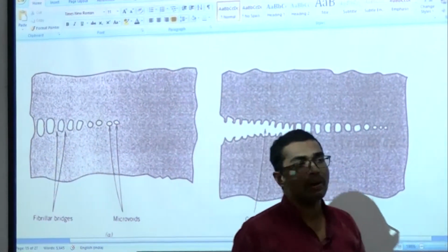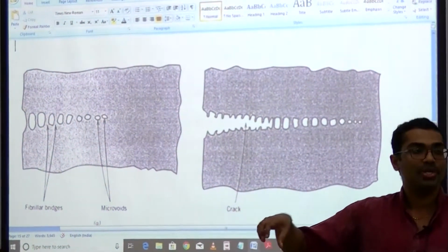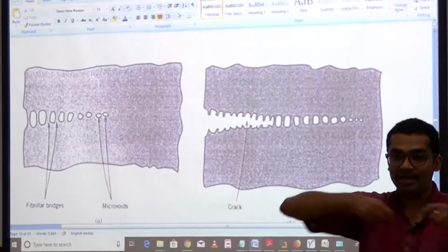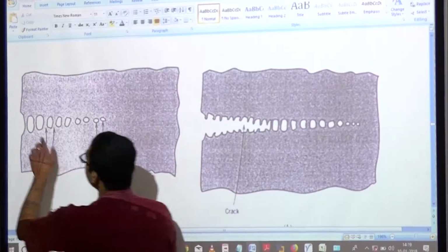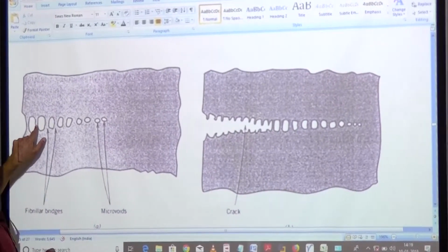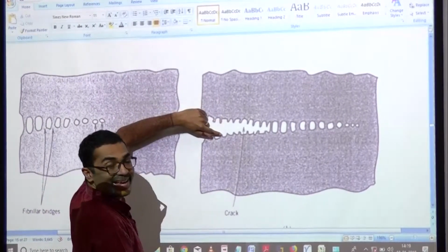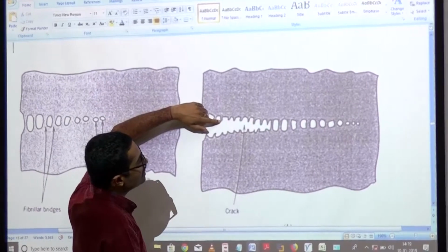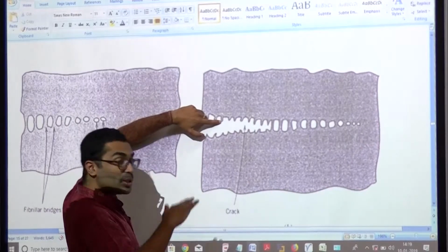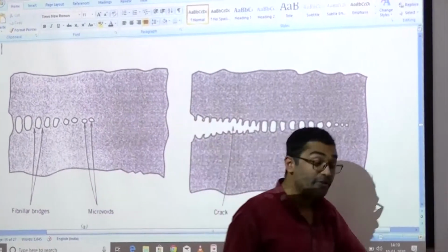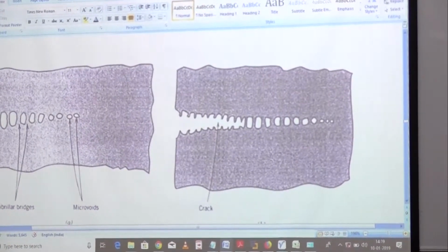And this is again perfectly analogous to what you would expect even in a metal, let us say very close to its melting point. You apply stress, and then you would have stress distributions that can result in micro voids and so on. And notice that this region is essentially where necking is happening. And if you notice this, at the tip of this there is necking happening. And that is the reason why if you looked at crystallinity here versus crystallinity here, you would expect more alignment and crystallinity here. So that distinction, by the way, gives you a lot of information about the mechanism involved in crazing. And this particular phenomenon was called crazing.